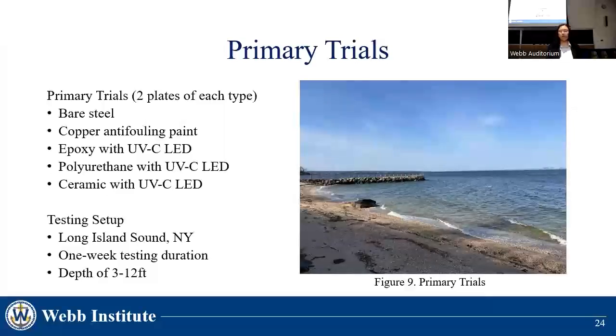Given the opportunity for practical marine growth in the Long Island Sound, the experiment was conducted at the Webb Beach with a design test window of 2 weeks of underwater exposure. This duration was selected to align with a plateau in marine growth. The test was truncated, however, to approximately 1 week due to harsh weather and was conducted between March 10th and